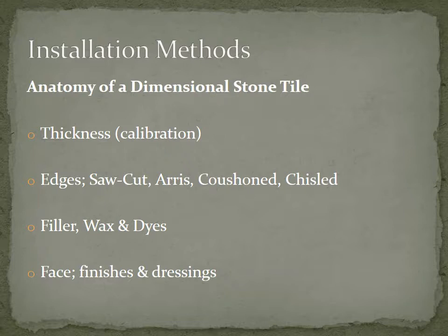Sometimes it'll just be a clear resin that dries hard, just something to bring out the natural color, or something to fill the pores so that the stone will hold the shine much better. Certain stones have pretty good sized voids, like travertine. Those are all filled in the factory with the travertine filler as part of the process, and then the grinding continues, and that fill ends up flush and it polishes consistently with the rest of the stone. Sometimes it doesn't polish consistently because it shrinks when it's in the void that it was filling, so it doesn't hold the polish quite the same.